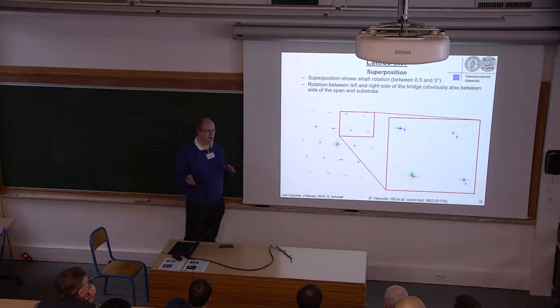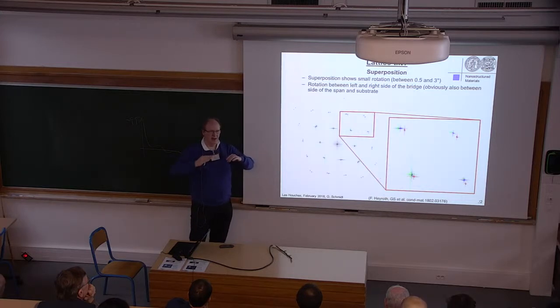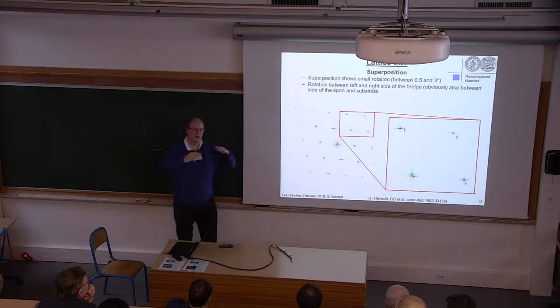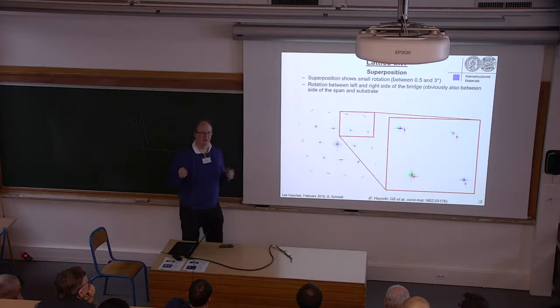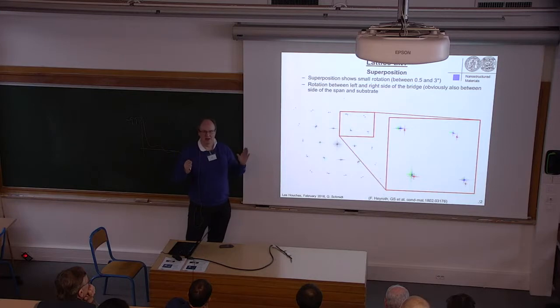It differs from bridge to bridge depending on the strain, but usually the left and the right side of the bridge are tilted against each other between 0.5 and 3 degrees. And also each side of the bridge is tilted towards the substrate maybe by 0.5 to 1.5 degrees. So there's not a lot of mismatch, and it's really the lattice structure from the substrate which is adopted and which propagates through the bridge, but due to the strain, you can imagine it crystallizes like this, and then it meets in the center, and that's why you have the defect, because you have a slight mismatch between the two sides.